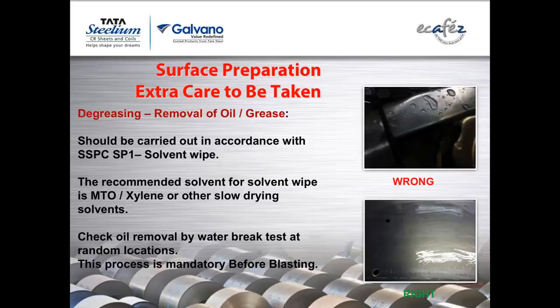Now there are a few slides where we are talking about surface preparation and what extra care needs to be taken. First and foremost, which I have already said is mandatory, is removal of oil and grease. It should be carried out in accordance with SSPC SP1 by solvent wiping. Apart from solvents, it could be immersion cleaners or other things also. The recommended solvent is usually MTO or xylene or some other slow drying solvent. MTO stands for mineral turpentine oil, and GP thinner, general purpose thinner, is also available in the market. You can buy that also, but it should not be contaminated. It should be in good condition.